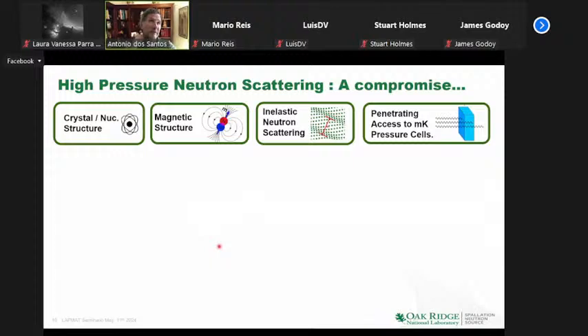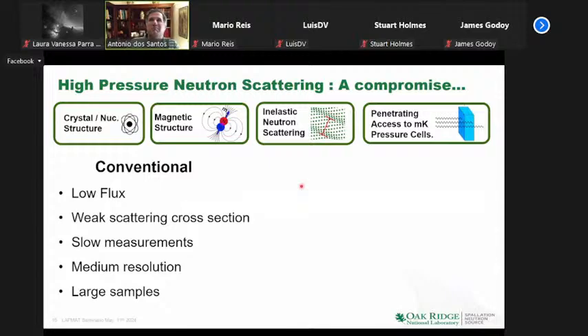Now, the coupling of high pressure then with neutrons is always a compromise, right? So I went over the little bullets of why neutrons are important, but as I said, it's lower flux than X-rays, synchrotrons, even Ramans. They have a weak cross section, so it's longer measurements. The resolution is not the best, and sometimes requires large samples.